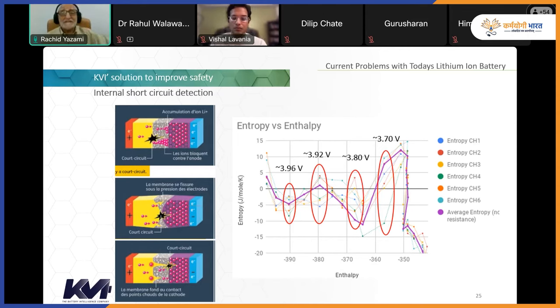Now, when you have a leak inside the battery, it is like a discharge, a self-discharge, and this discharge will affect the voltage. So the voltage will drop by a fraction of a millivolt, 0.1, 0.2 millivolt, which is the same order of magnitude as the millivolts that we measure from the temperature derivative. So we have two phenomena: one is the thermodynamics, and the other is the internal leak, which are in the same order of magnitude. This means that by measuring entropy, we can see whether a battery has an internal short circuit just by comparing the entropy data of a battery that has no internal short circuit and the one that has an internal short circuit.